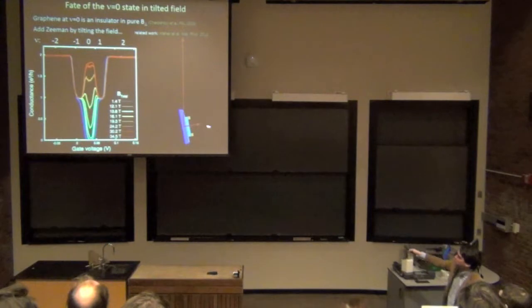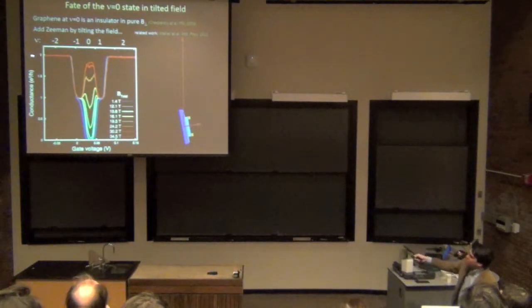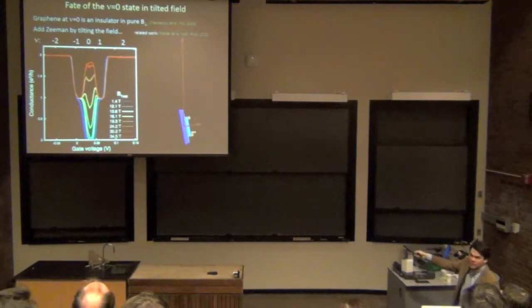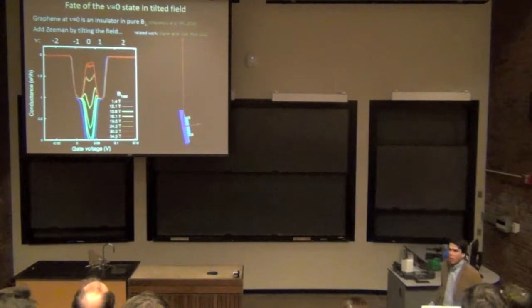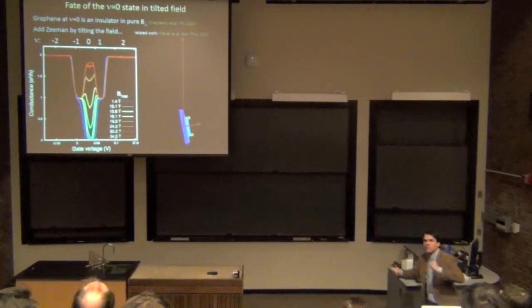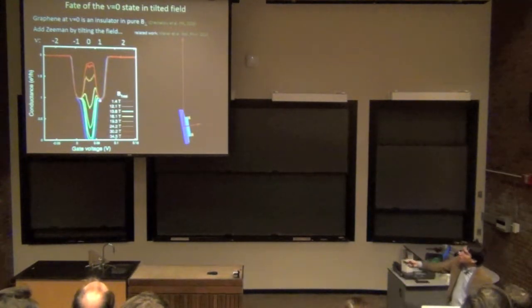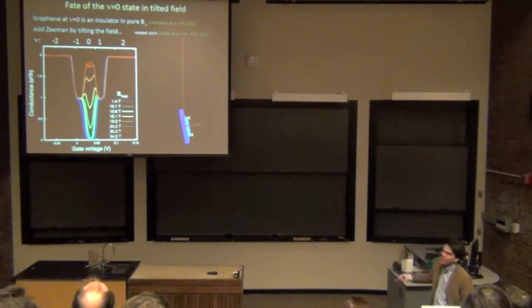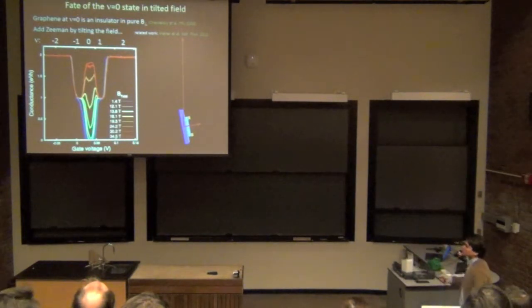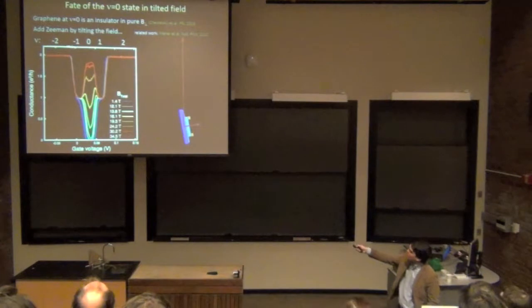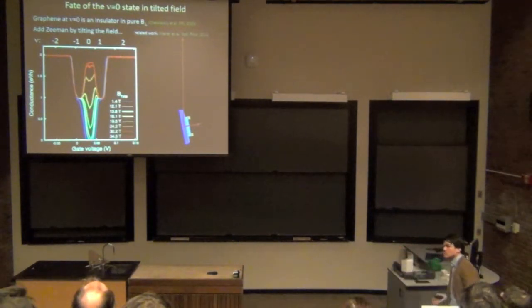So the game that we're playing here, just to give you a little insight into why this funny picture is here, is that the overall structure of the Landau levels is controlled by the out-of-plane magnetic field. So when we add an in-plane magnetic field, all we're doing is playing with the spins of the system. All we've done here is add an immense amount of Zeeman energy to the system. So what this looks like is that maybe we've induced this quantum spin Hall state in graphene.